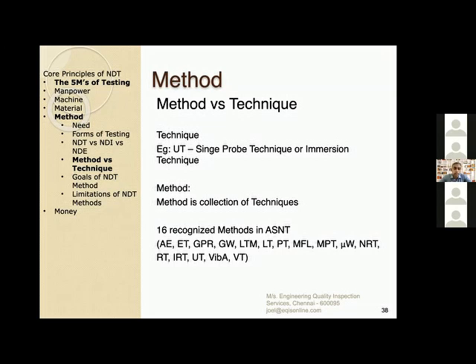So I will quickly run through the different types of NDT methods. Acoustic emission, AE stands for acoustic emission. Acoustic emission is where we listen to the sound emitted by metal when it is subjected to a crack. You fix a sensor to a metal and it keeps listening to that sound 24 hours a day, 365 days a year. And when there is a crack, it's going to create a small noise. And this noise is captured in the acoustic emission technique, which is a permanent setup, and it will monitor continuously.